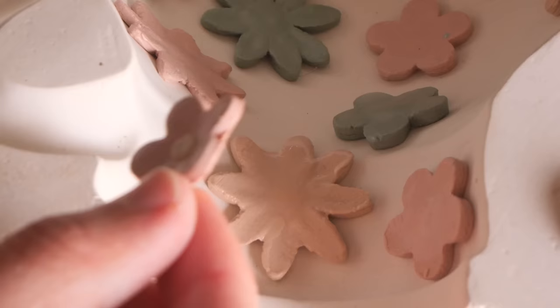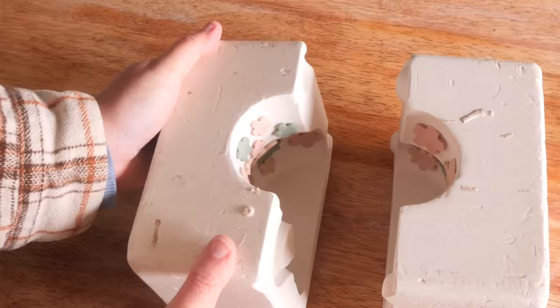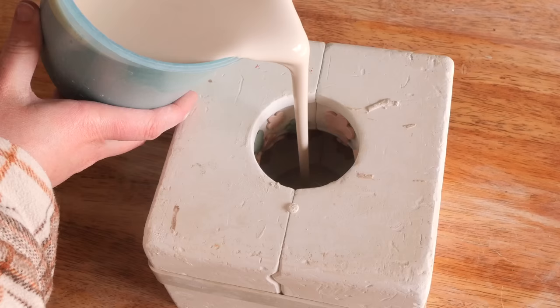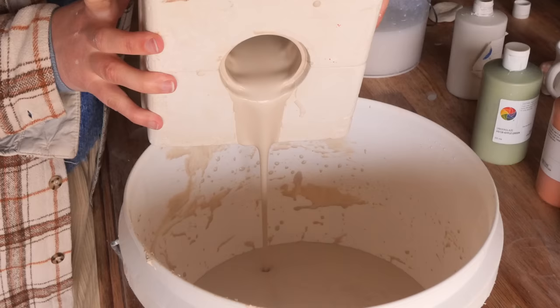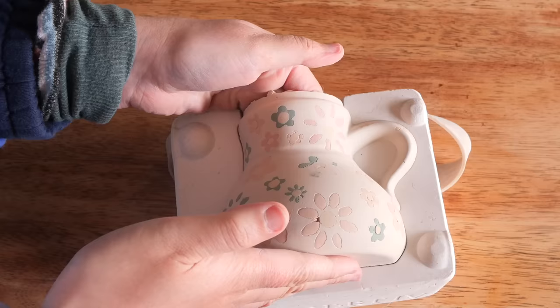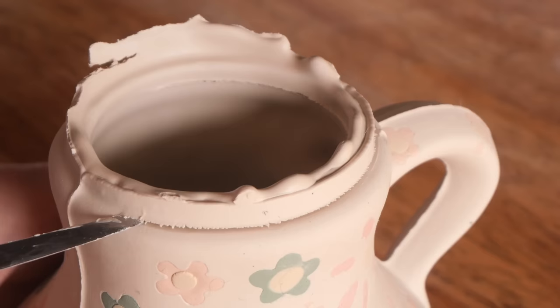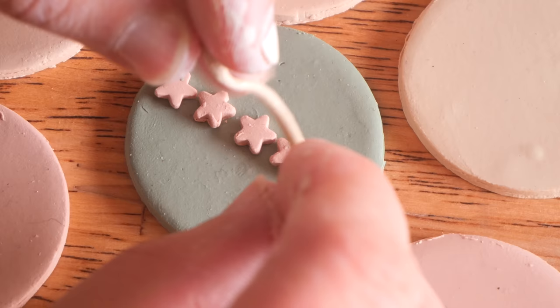The way I put the design inside was I got a little spray bottle and sprayed it with water. The way slip casting works is that the plaster is dry and porous so it pulls the moisture out of the clay, leaving that solid shell you see when I open the mold. I needed to dampen the surface of the plaster so the clay would stick without drying out before I added the slip. This was really difficult — because the clay was drying out constantly as I was adding more flowers, I had to keep spraying it constantly. I actually thought this design would save time, but it's just as hard as painting a piece with illustrative detail. When I opened the mold, I discovered the inlay design wasn't pushed flush against the plaster, so some slip had pushed underneath the design, meaning the flowers weren't as sharp as I intended.